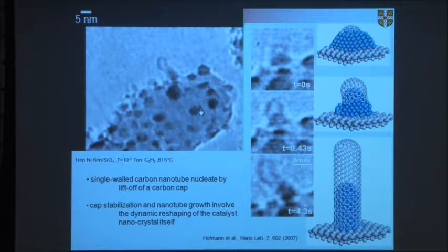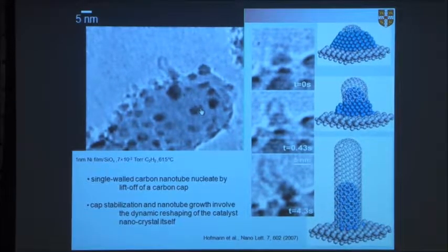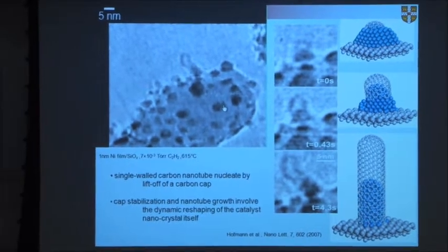And this highlights the problem we've got with carbon nanotubes in the control. It's very difficult to actually control the diameter and the actual type of nanotube you grow. Even when you start playing with the catalyst and the growth process, it's still very difficult to see exactly what's going on. In this case, we think it's something to do with the fact that if you have a lot of carbon coming in, which you get when you have a wide-based nickel, enough carbon comes in below here to push this off. In this case, there isn't enough, and so the nickel stays at the bottom and the tube grows up. It's the same when you use iron as the catalyst or cobalt. It's very difficult to actually control the growth precisely so you get exactly the same type of nanotube every time you grow. That's one of the big problems with carbon nanotubes.